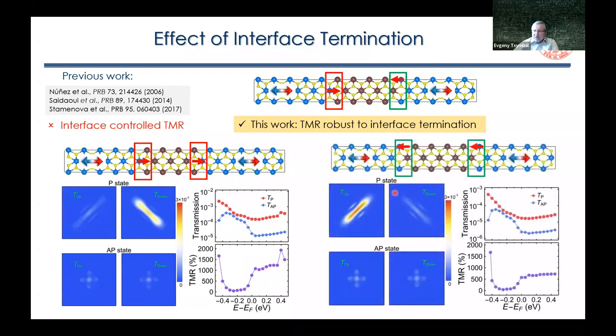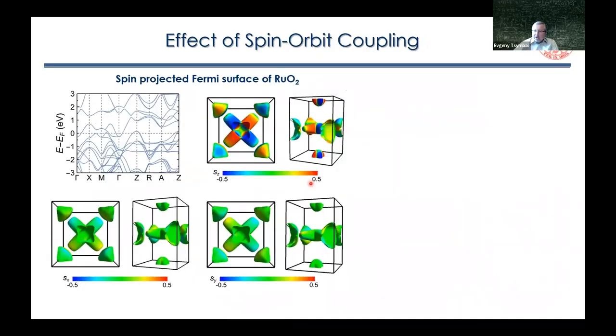So if we now switch the moments, we change the interface termination in such a way that these moments are pointing in opposite directions, we have a similar picture. We have very similar distributions and still very sizable TMR. So basically from this analysis, we can argue that interface termination is not critical. And in experimental conditions, we should expect robust TMR independent of interface termination. So another point to consider is spin orbit coupling. All the calculations I've shown before were performed in the absence of spin orbit coupling, because all the splittings I've mentioned are not driven by spin orbit coupling.